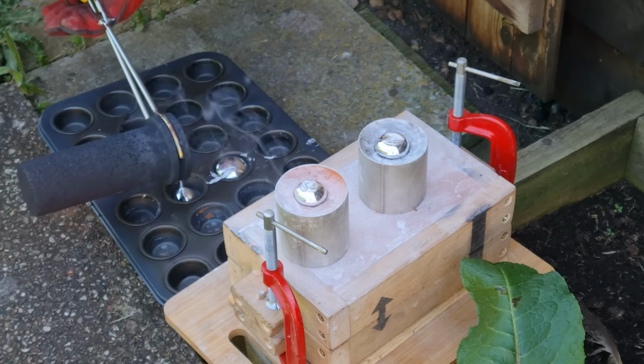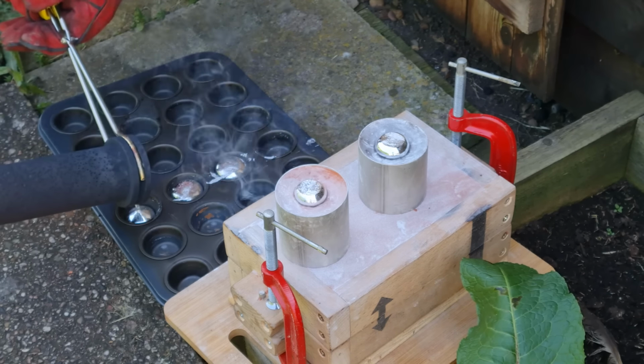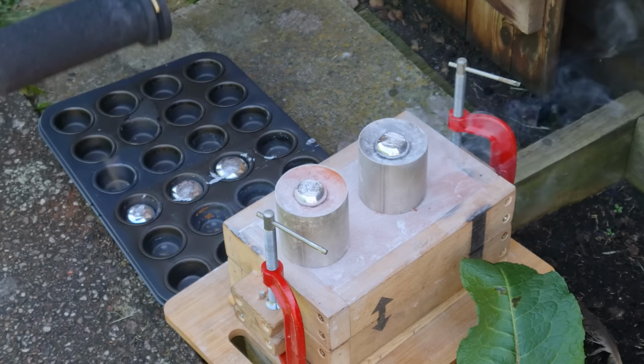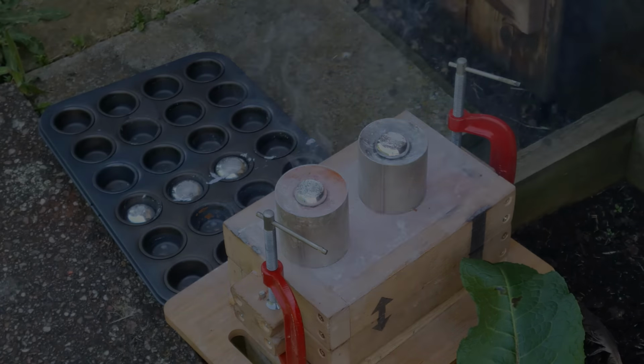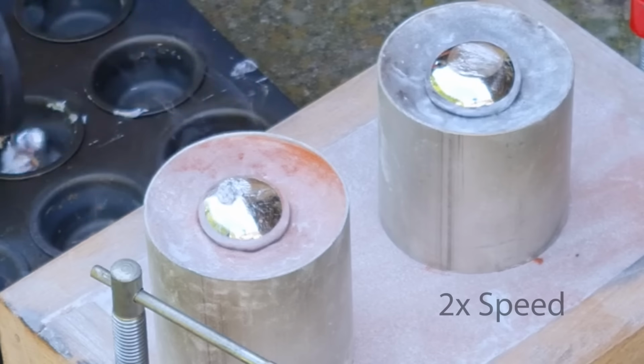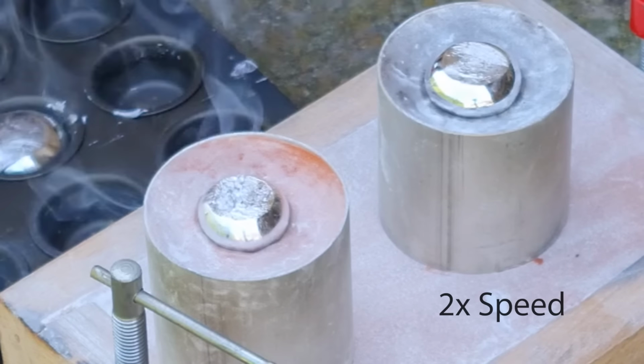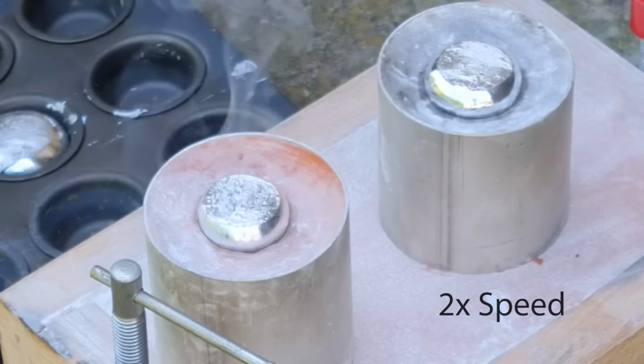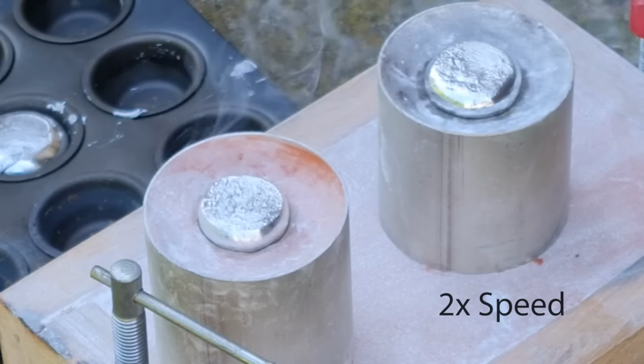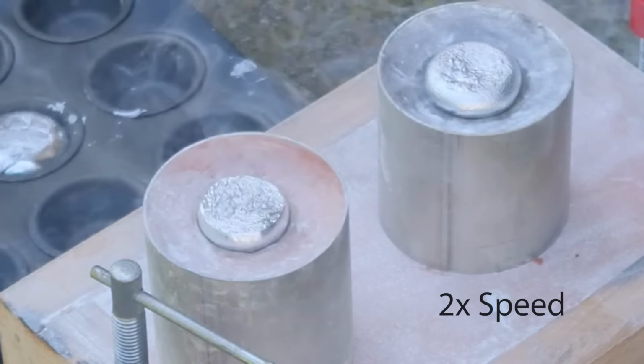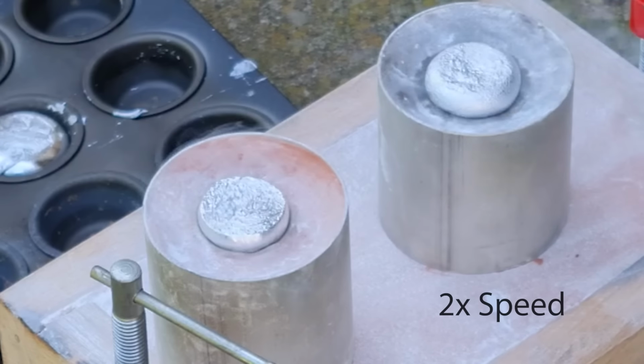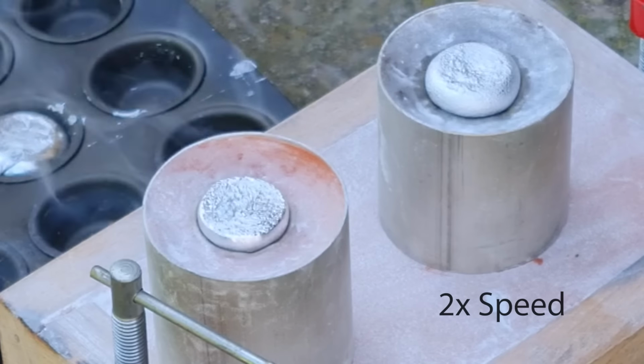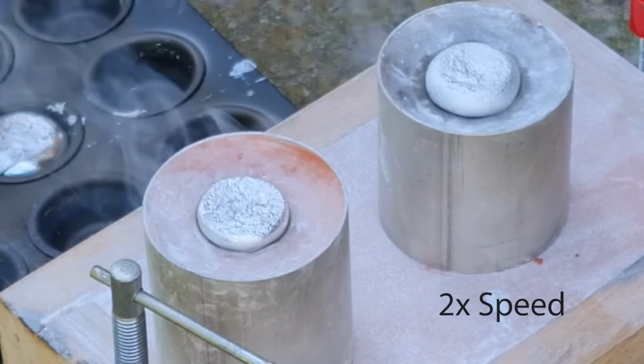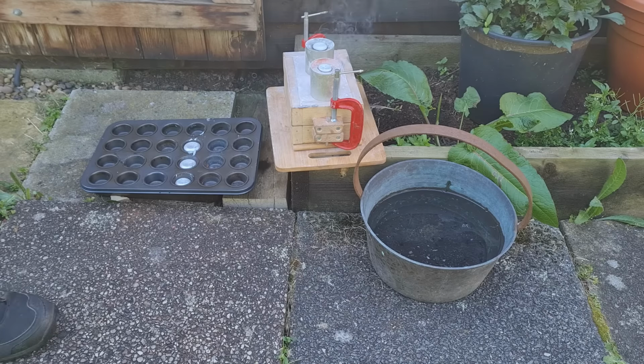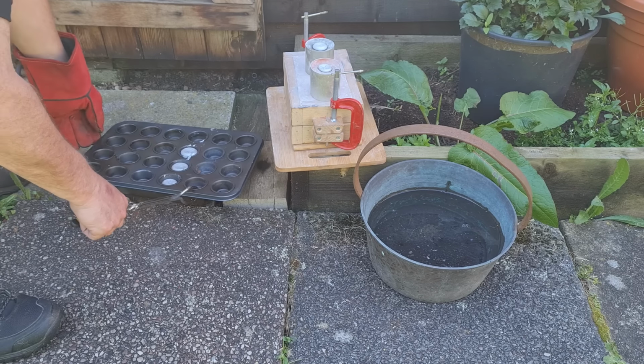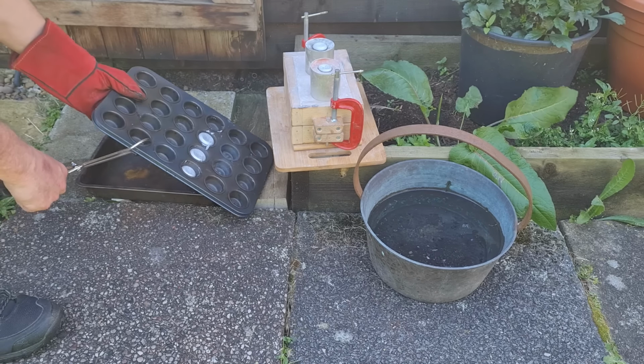Any excess metal left in the crucible is then poured into ingots in a muffin tray, ready to go back into the melt pile. The cooling of the casting causes the metal to shrink, so to prevent this, the feeder continues to supply the casting with molten metal, and you can see this happening on the top of the sprues as the metal collapses in. After a few minutes, the ingots have solidified and are quenched in the water.